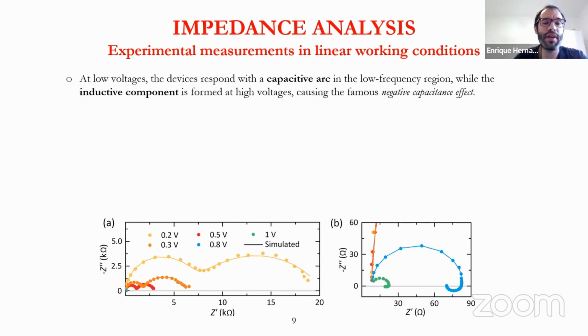We obtain more or less the same characteristics as in solar cells and photodetectors. The Nyquist plot at low voltage shows two capacitive semicircles. This is the high frequency feature correlated with bulk processes. Here, the low frequency feature correlated with interfacial processes, more or less. The size of the Nyquist plot decreases with the bias point, and when one applies high voltage, in line with the bias point, one obtains this feature. Okay, in the Nyquist plot it collapses the real axis, and goes below to the fourth quadrant. This is a negative capacitance feature, or chemical inductive feature,